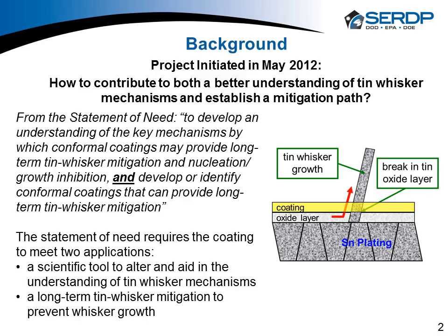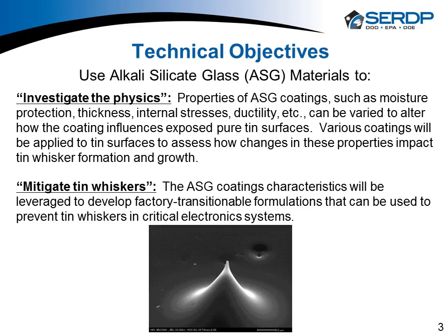I'm on slide 2. I'm going to go to slide 3. And Rockwell's approach is to look at a family of materials called alkali silicate glasses. And one we have been using, as I'll talk in a couple of the other slides, we've been using the ASG, or I call it liquid glass, in some other systems, so we thought it was applicable to whiskers. And more importantly, the properties of liquid glass, the ASG coating, they can change how moisture goes through surfaces. They're very tailorable, and we felt that it was a system that offered some advantages to how we could impact tin whisker formation and growth.